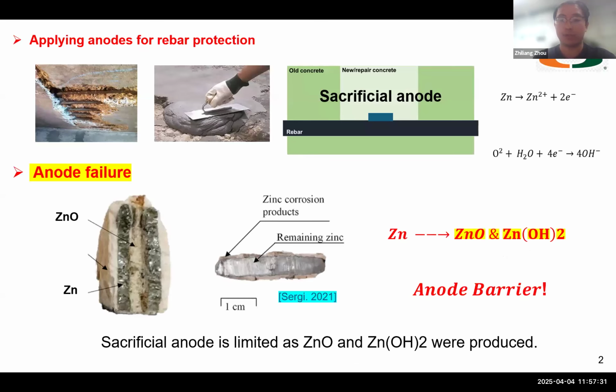I would like to go through the whole story with you. Sacrificial anodes are used in salt-contaminated concrete to protect the steel rebars from corrosion. The sacrificial anodes, basically made of zinc, are able to produce and deliver current flows to the rebars, so the rebars are protected by the anodes. However, these sacrificial anodes usually have poor durability with reduced protective current over time because a lot of anodic products are produced at the surfaces of sacrificial anodes.